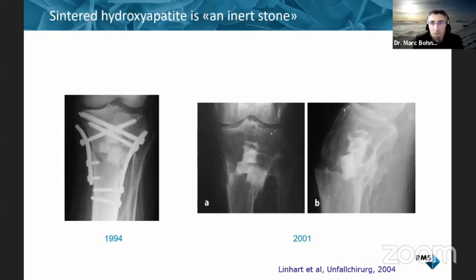If we come back to the work of Bill Bonfield, one may wonder how the silicon, or the silicate, can really have a biological reaction or effect on hydroxyapatite, because hydroxyapatite, the sintered version, is pretty inert once implanted in the body. And this is an example of a clinical study by Linhart in Germany, showing basically that nothing happened to the sintered hydroxyapatite after 7 years. So Bill Bonfield always mentioned that silicon or silicates were included in the structure of hydroxyapatite, but if the hydroxyapatite never dissolved, how would the silicon or silicate affect the biological reaction?